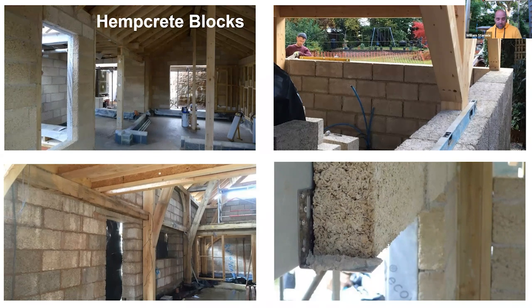The blocks work very well with a feature oak or glulam frame. There's an oak frame in the bottom left and glulam top right. The blocks can be as large as 300 or 400 millimeters wide, so that you just plaster the inside of them and render the outside. If you're worried about cold bridging through the mortar, you can use an insulating mortar or have two skins of blocks and stagger the joins.